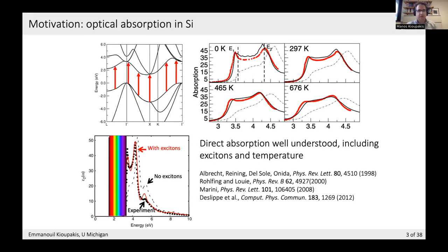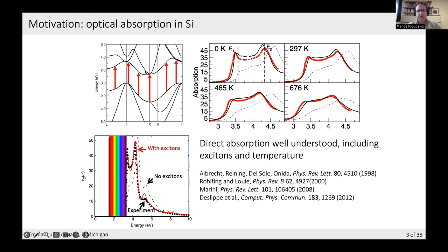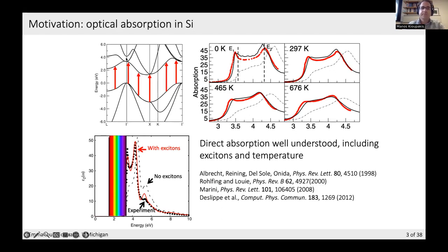We'll start with the case of silicon, the simplest material with an indirect band gap. What you see here is the band structure of silicon — the valence bands and the empty conduction bands. We're considering optical transitions from an occupied state to an empty state. Now, photons at this scale give us energy but not much momentum. So in this diagram you would see a vertical transition: energy comes from the photon, but not much momentum, so the momentum of the electron remains pretty much the same in this direct optical transition.